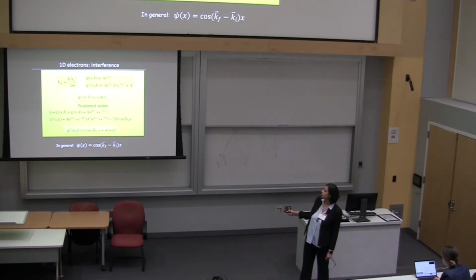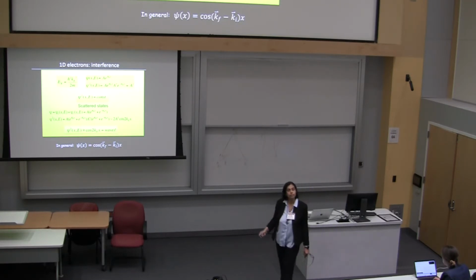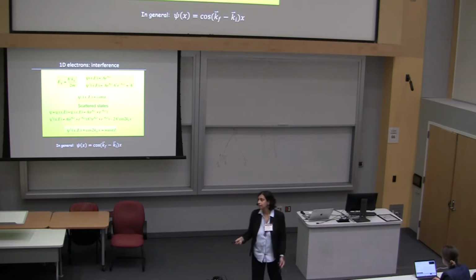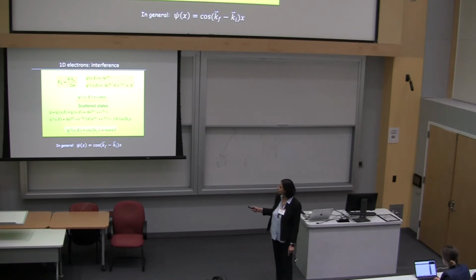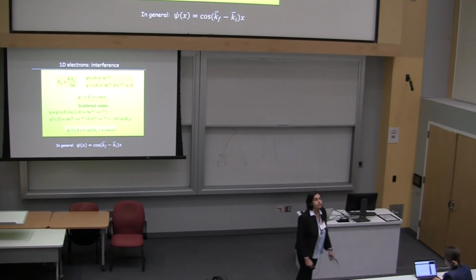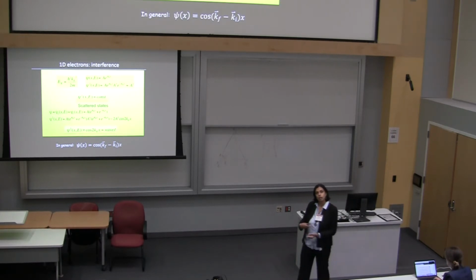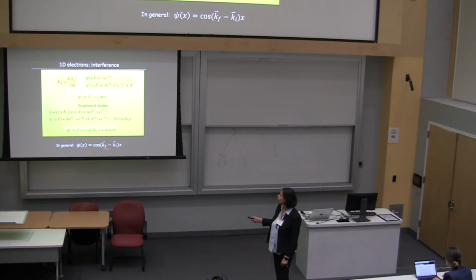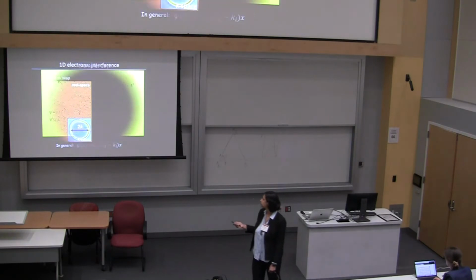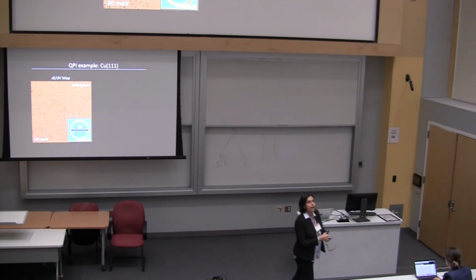And now when you square the wave function, you get this kind of a cosine term, and that gives you waves. So in general, if you have scattering, then psi squared is proportional to cosine of the outgoing minus the incoming momentum, times x. Okay? So this is how you get information on momentum using STM. So this is just an example.